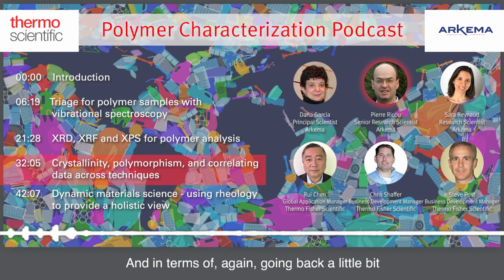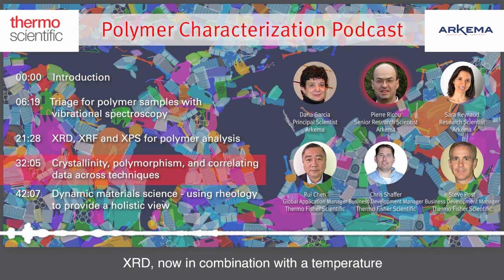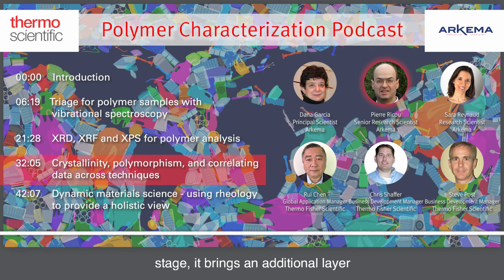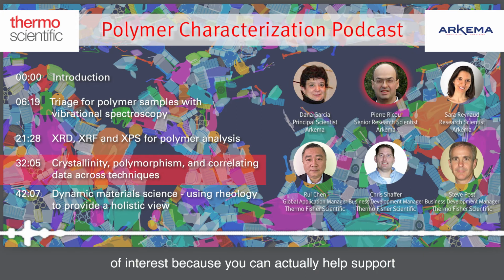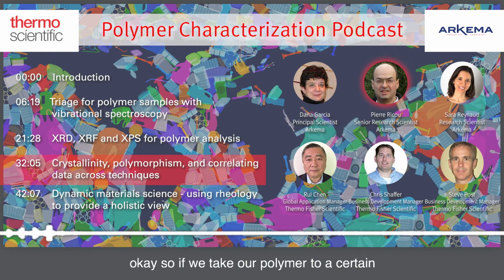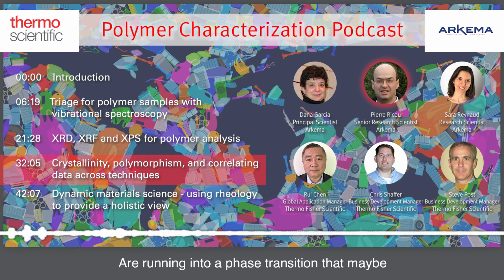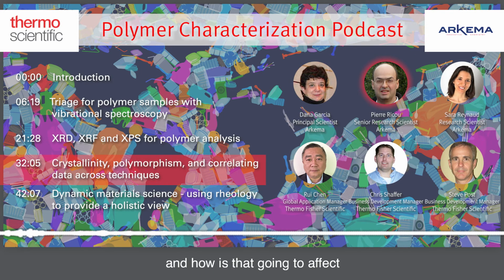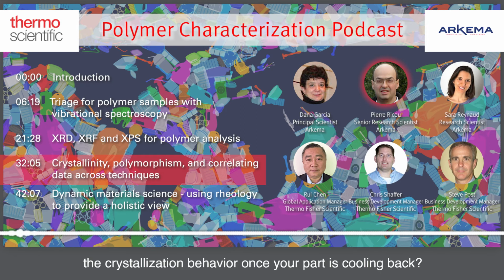Going back to processing, having the wide-angle X-ray scattering technique, XRD, in combination with a temperature stage brings an additional layer of interest, because you can help support process development by understanding: if we take our polymer to a certain temperature, how long will it take to develop a certain crystallinity? Are we running into a phase transition that you may or may not want? And how is that going to affect the crystallization behavior once your part is cooling back?